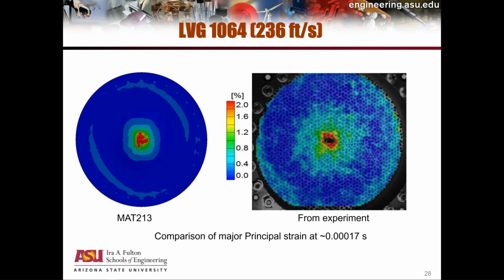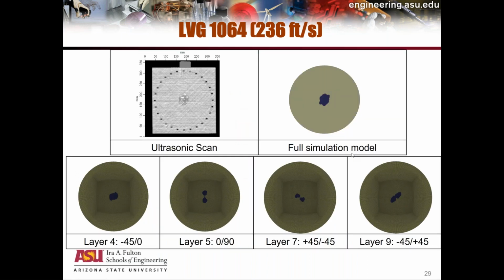And we have here pictures showing what the percentage principal strain is on the plate coming from the computer program versus what the DIC data tells us. You can see a little bit of damage here, but otherwise most of the plate is intact. So after the testing was done, NASA took apart this plate, did ultrasonic scan images to come up with a diagram that shows where delamination occurred in those 15 layers in between the 16 plies. And these are the predictions coming from the computer program.